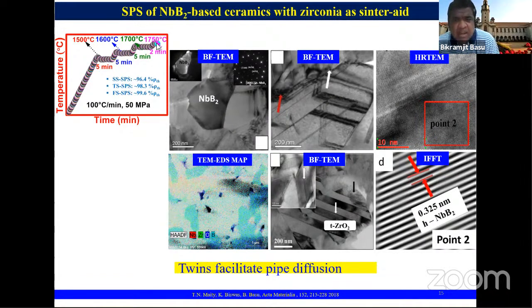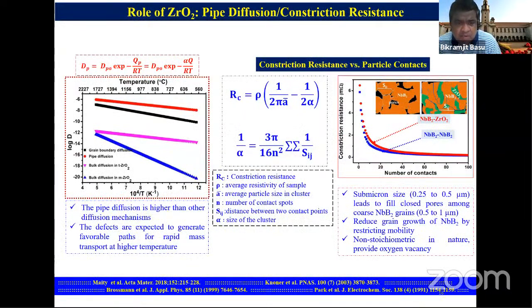And if you see this array of transmission electron microscopy images, you can see hexagonal niobium boride is retained, and we can see a lot of defect structure in terms of twins, stacking faults, and so on. The interplanar distance that we have measured is around 0.325 nanometer. So essentially, what I would like to show you in the next slide is that this defect structure allows us to understand the core mechanism of densification in these niobium diboride-based materials.